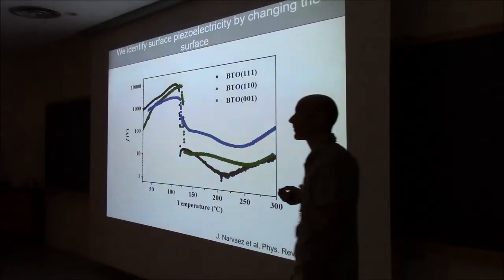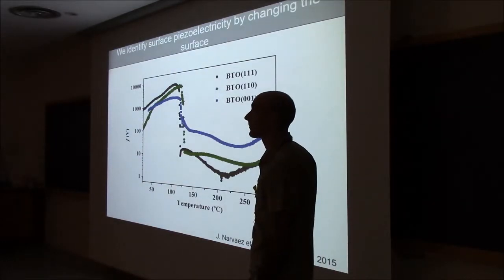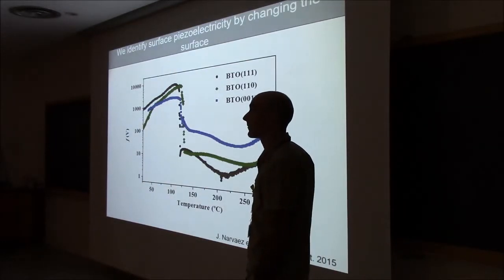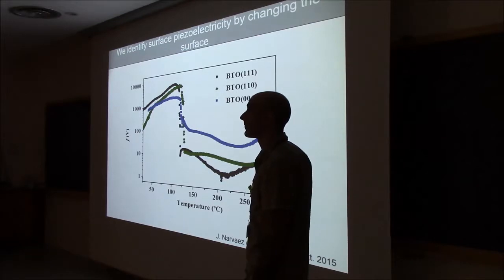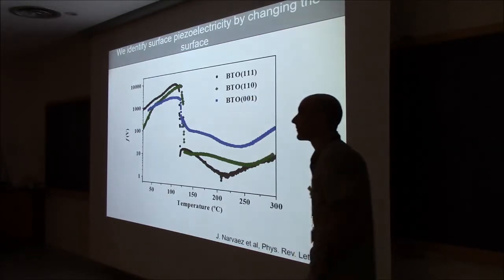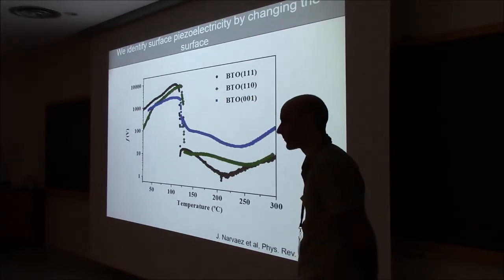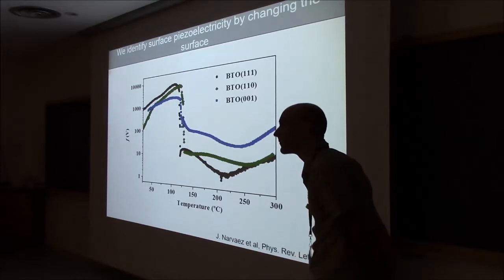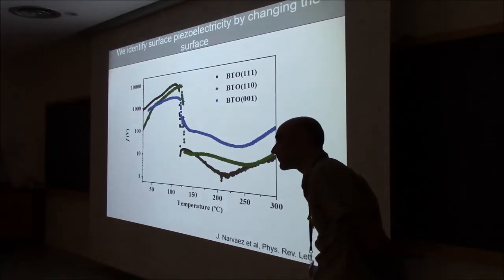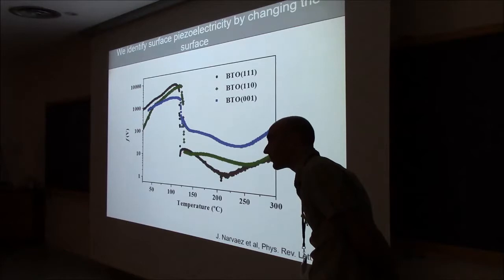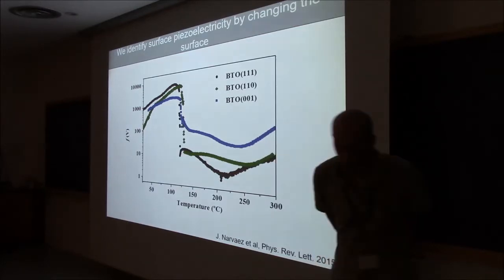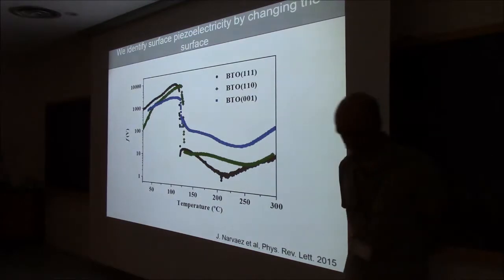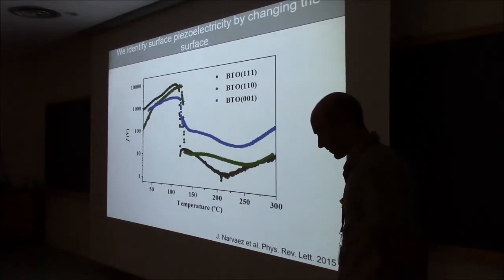Regarding the surface piezoelectricity, if I take a surface which develops some polarization, I neutralize the polarization by putting some hydrogen on there, or H minus or so, and then I start bending it. How much do you think you can reduce surface piezoelectricity in this way? Will it be completely or just a factor of?